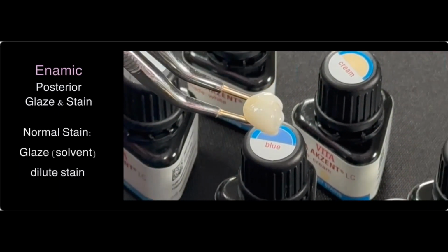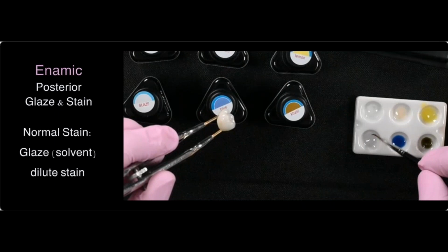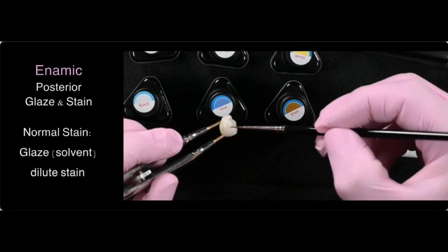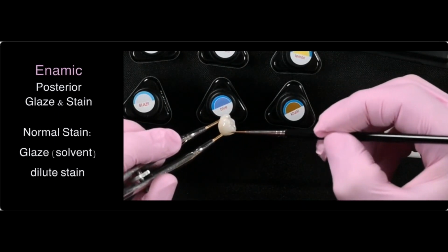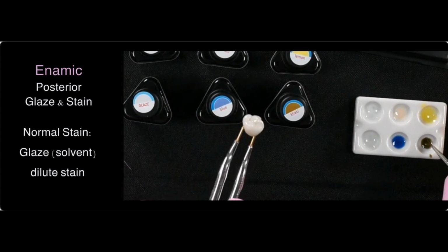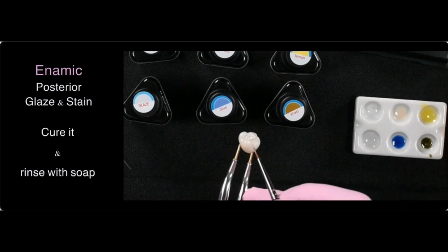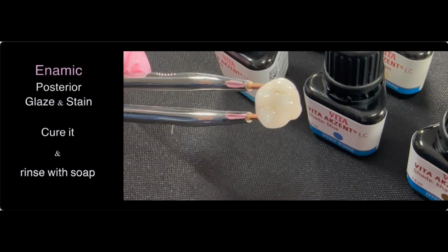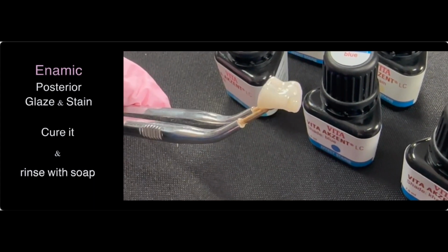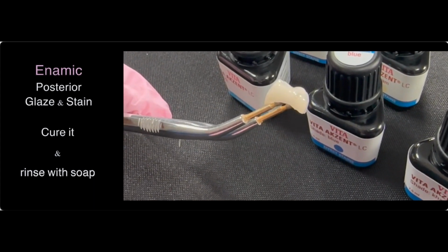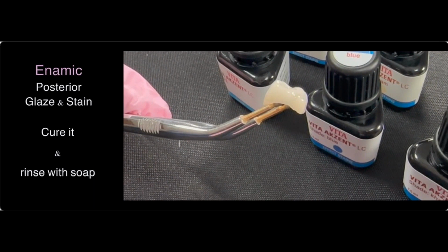All this, if you don't like it, you have a little gauze next to you with a little bit of alcohol, or there's a thinner that also comes, a bottle, that you can just wipe it right off and start over. You do 20, 30 of these, and you're going to become really good. And you can do this in the patient's mouth too. You put it in the mouth and you paint it in and take it out and glaze it. So these are how you can light cure glaze enamic restorations.